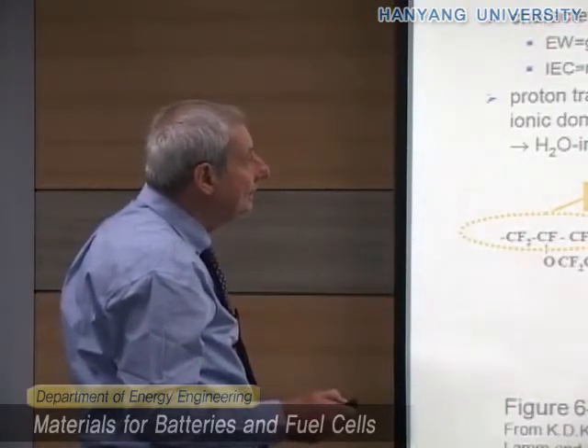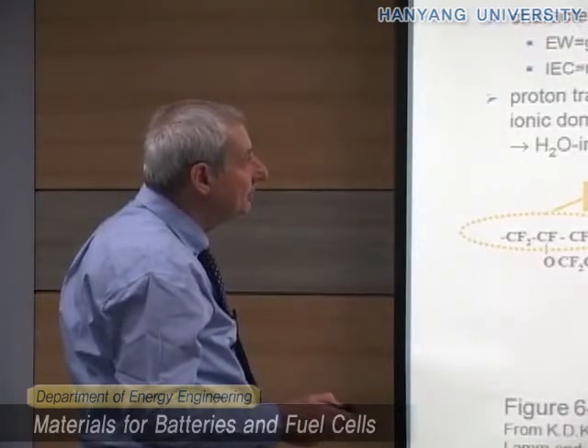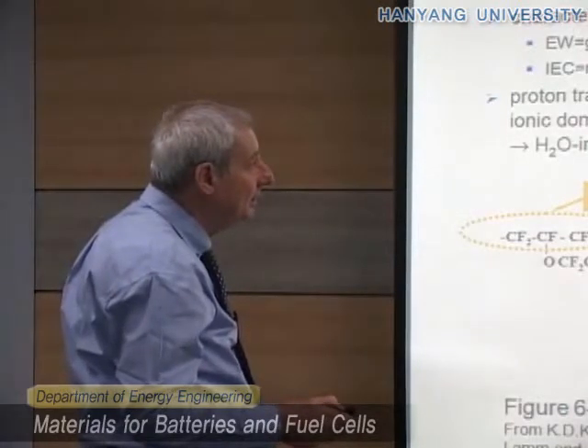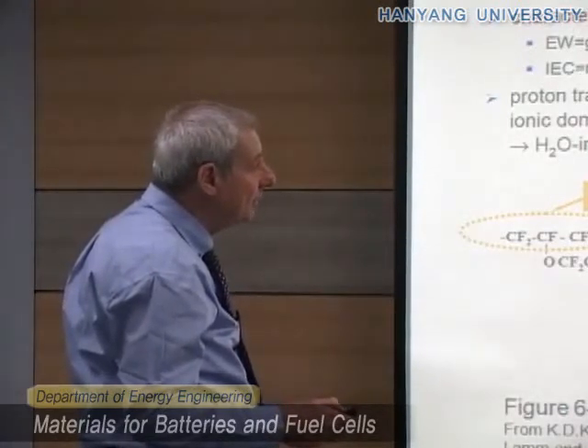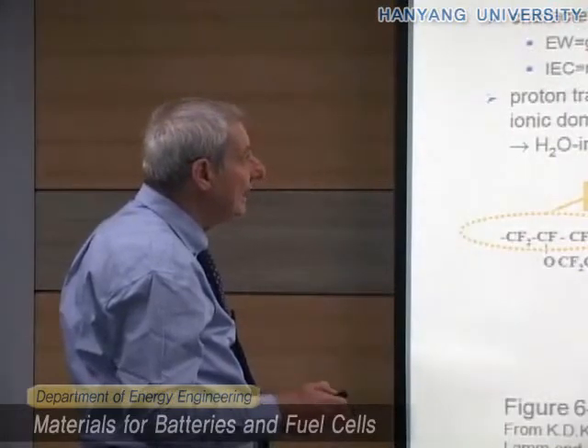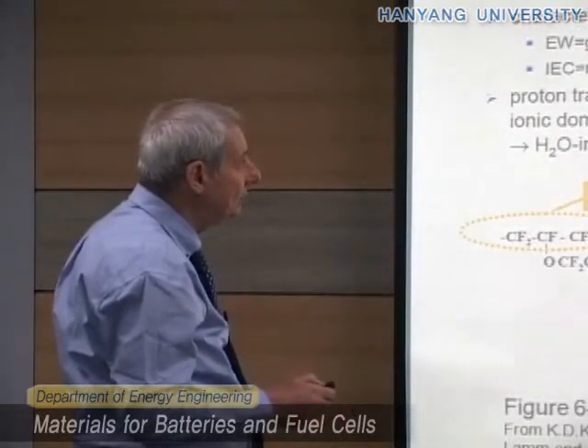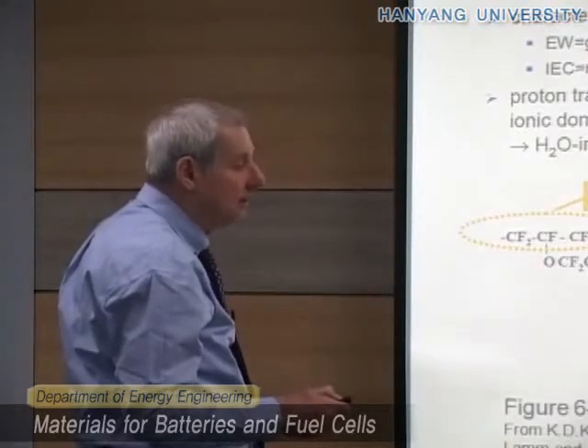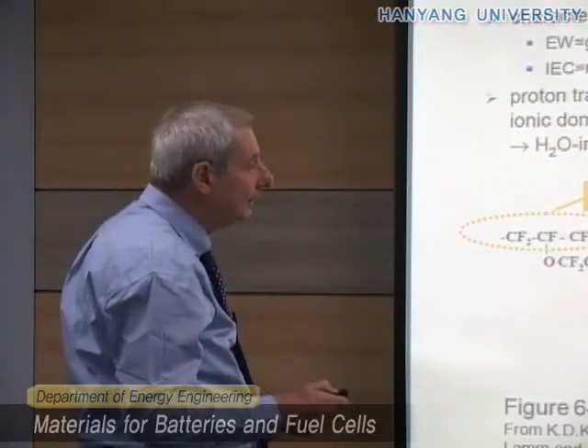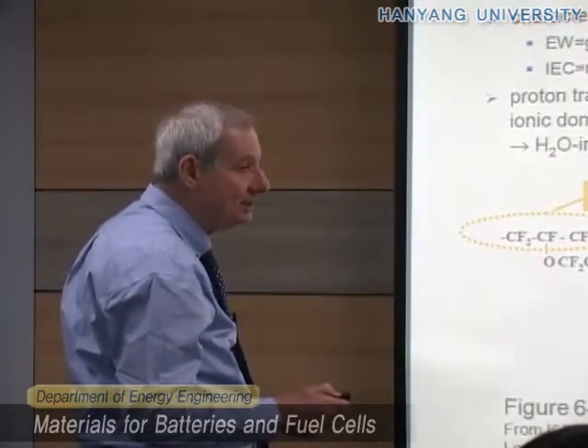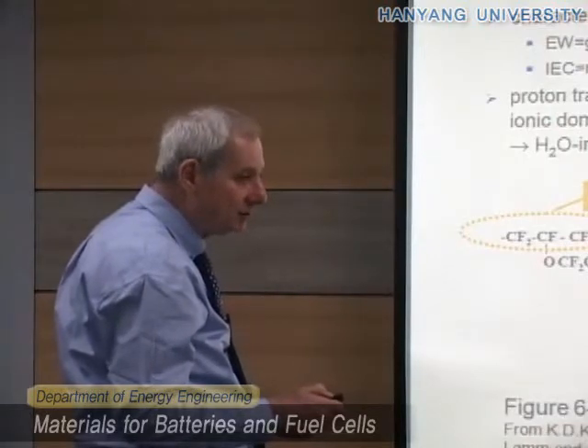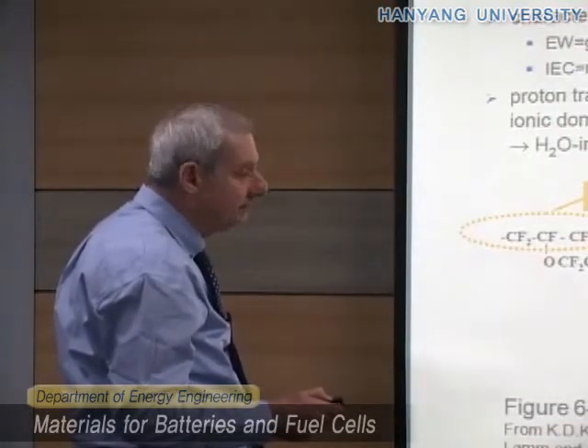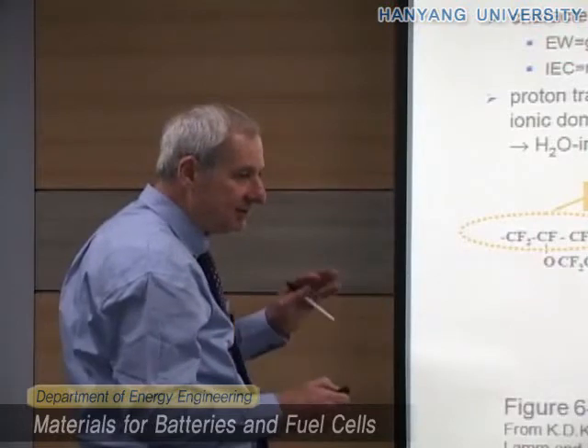Now you understand that the proton transport depends on the hydration state, but we can always have some problem with fuel crossover. So the hydrogen, instead of reacting at the anode, can go all the way to the cathode. And then at the cathode, instead of having reduction of oxygen, as we like, we are going to have a reduction of hydrogen, and this kills the cell.